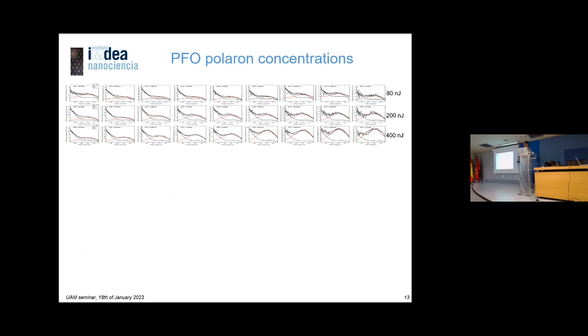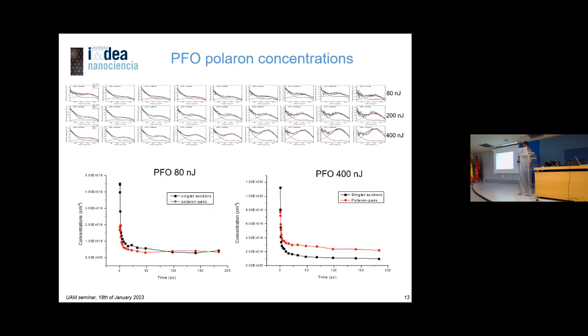So we do spectral reconstruction, forcing it to fit all the data sets, which are on the order of 50 different time frames for 3 different pump energies. When you do that, you can obtain the time-dependent concentrations, given by 2 different energies.